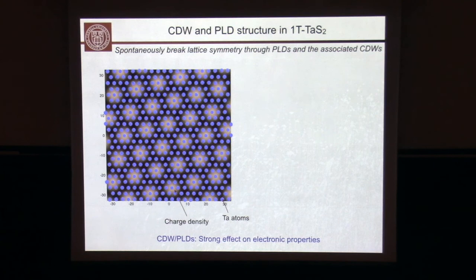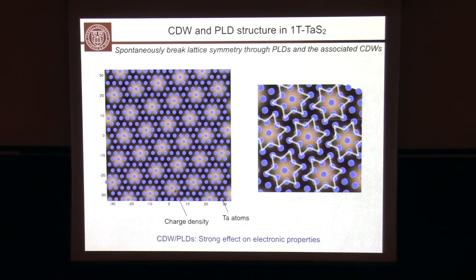This picture shows the formation of these stars of David, which shows you this symmetry breaking of the crystal as the charge density wave emerges. In these, the charge density wave couples very strongly with PLDs, or periodic lattice distortions. In the STEM, as a probe to measure position of atoms, we can get directly to the lattice part of this. Okay, so the charge is a different story. That's when we need to use EELS. For now, I want to talk about mapping the structural order parameters.